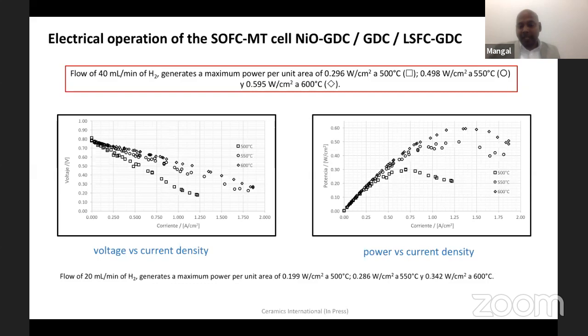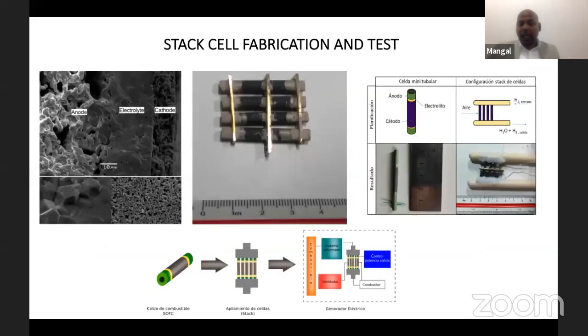So these fuel cells, finally we tested, and it gave nearly 0.6 watt per centimeter square at 600 degree. And then later we stacked the cells, and in our case, maximum we reached 0.8 to 1 watt. When we stacked the cells, for example in the case of 4 cells, it has to have 4 watts. But in our case, we used the converter. The converter has the opportunity to give multiple times the energy. So in our case, it gave more than 4 if we stack 4 cells. We stacked 10, then it gave 15 watt.